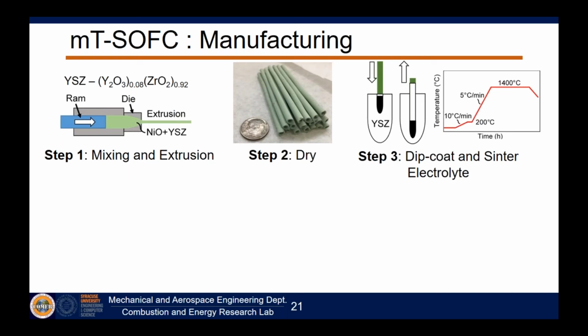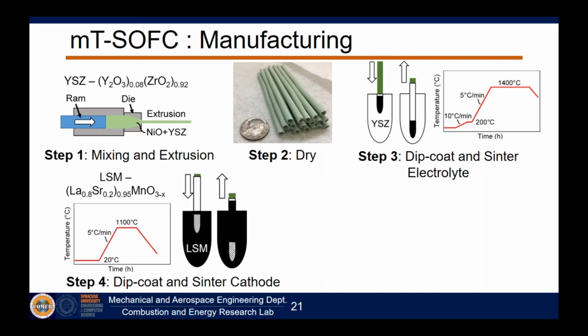We then dry it, and ultimately we'll sinter it up to 1400 degrees Celsius where that electrolyte material will densify properly. We then take that electrolyte, or the fuel cell with the electrolyte on, and dip it in a cathode material and allow that to dry and then sinter it to 1100 degrees Celsius. If you're curious about the temperatures, we can talk a little bit more about that, but different materials need different sintering temperatures.